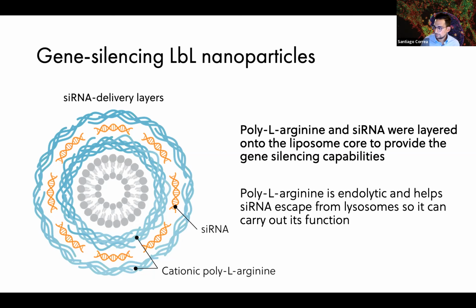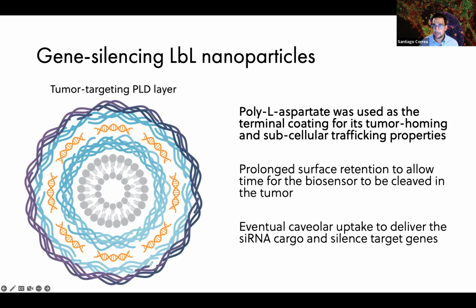particular target gene. Now, to protect these therapeutic layers, we add our outermost layer, which again is that polyaspartic acid, or PLD, system, which is tumor targeting, but also exhibits that sort of dual localization to the exterior and the interior of the cell. And that's really, really important for this particular system because the protease cleavage has to happen in the extracellular compartment, and the gene silencing has to happen in the intracellular compartments.